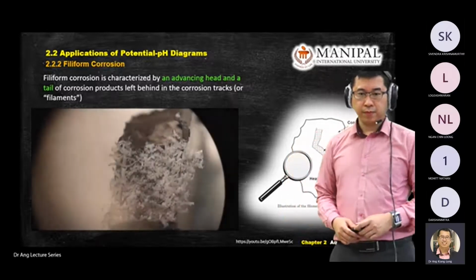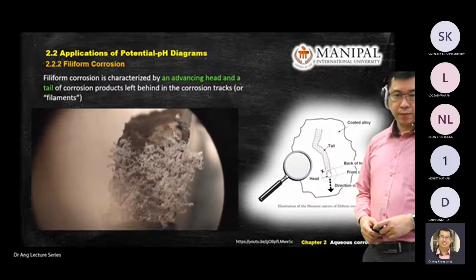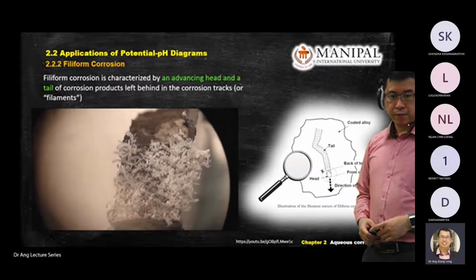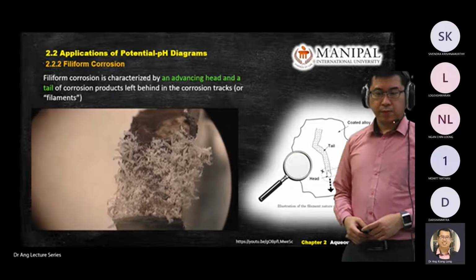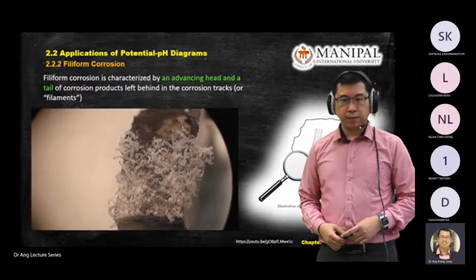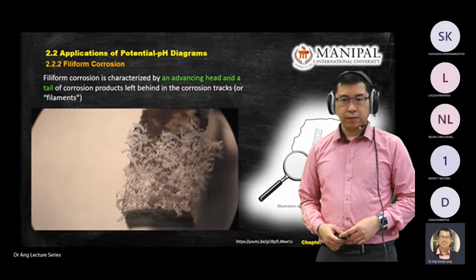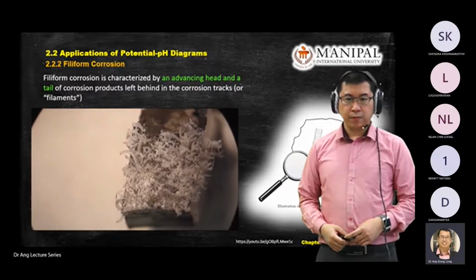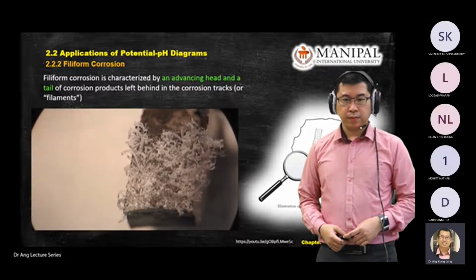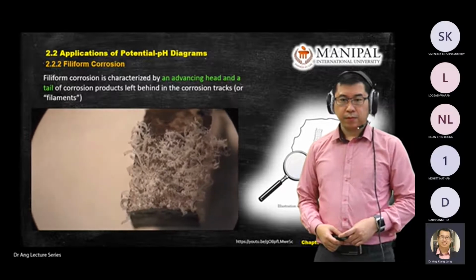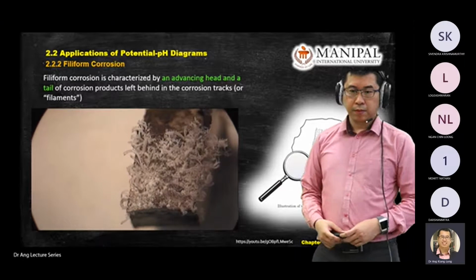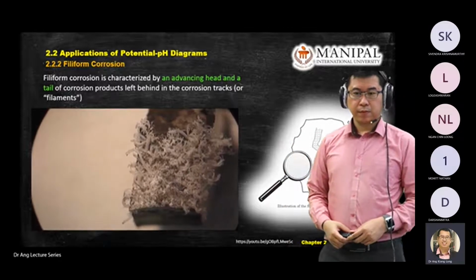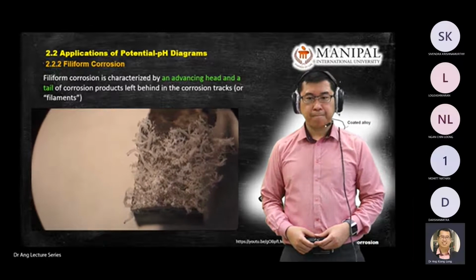Here we have a lovely example of filiform corrosion taking place on the surface of a freshly broken piece of aluminium. The aluminium had suffered mercury liquid metal embrittlement, and when washed and examined under a low power microscope, it was noticed that the aluminium was reacting with the wet mercury to form tubes or filaments of aluminium oxide. The video was taken using a handheld digital camera which just happened to be available at the time. We've speeded up the video to better illustrate the effect. Unusually, the filiform corrosion is producing filaments coming off the surface. This is probably because there are tiny droplets of mercury causing the corrosion to take place, and the corrosion product is forming right around the droplets as a ring. As further corrosion takes place, this ring is continuously pushed away, forming the tubes observed.